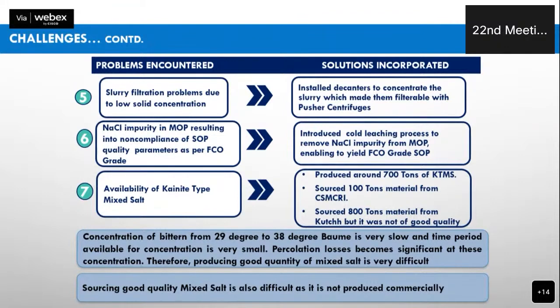We sourced around 100 tons material from CSMCRI. We also procured around 800 tons material from Kutch, but it was not of good quality. When we concentrate bittern from 29 to 38 degrees Baume, because of higher concentration, the evaporation is very slow, and percolation losses become significant. So this was one major problem. And sourcing good quality of mixed salt is also difficult, because mixed salt is not produced commercially.